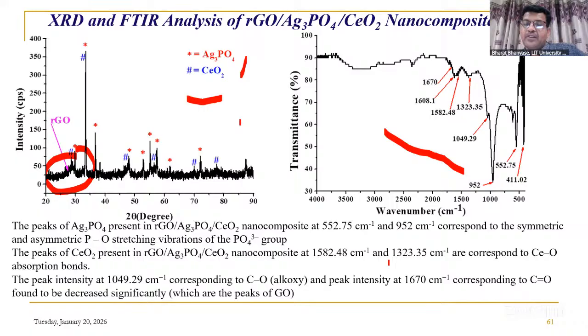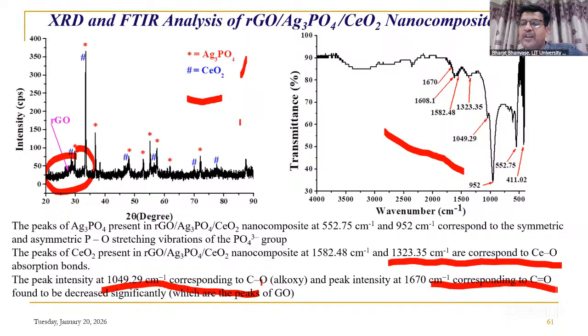It also confirms some functional groups present here: the peak around 1323 is cerium oxide, 1049 is C single bond O, 1670 is C double bond O, which again confirms graphene oxide. Then at 552 and 952, that corresponds to P-O bonding, which comes from the PO4 3-minus functional group.